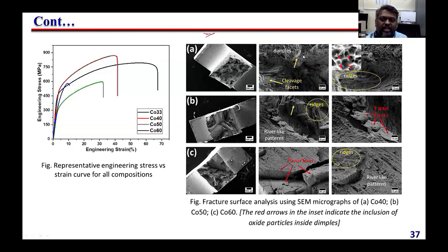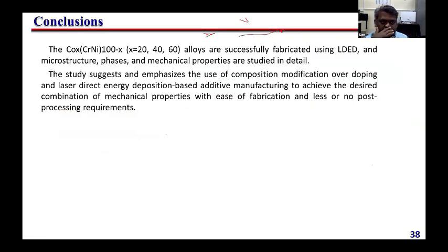Here you can also see fractography images, which we took after the tensile test. Here we are not seeing much of the dimple structure. In the first case dimples are there, but if you come to 50 or 60%, there is no kind of ductile behavior, no dimples, right? Instead, planar facets or ridges are there. So these indicate that it is having a brittle structure.